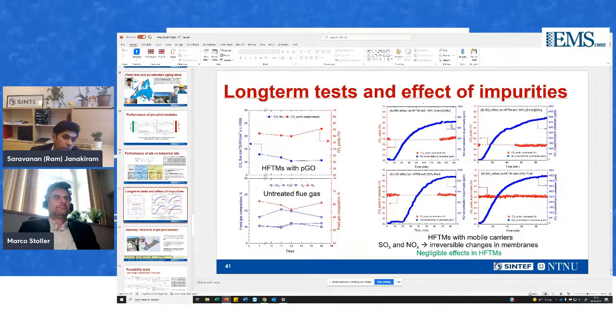That is what is important, because when the NOx or SOx irreversibly reacts with the mobile carriers or the carriers present in the membranes, then you will see an eventual drop in the CO2 purity, because now the carriers don't have an effect on CO2 transport. But that we did not see. We saw that the CO2 purity was very stable.